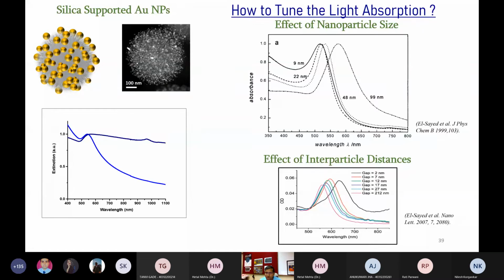And how do I change the light absorption properties of the nanoparticle, in this case gold? Two ways. One is by changing the size. If I change the particle size, you see 9 nanometer absorbs around 550, 560, whereas 99 nanometer absorbs around 600. So that way we can tune. But what is happening? The light absorption lambda max is changing from one wavelength to another wavelength. It is not becoming broad. So simple particle size change will not help.